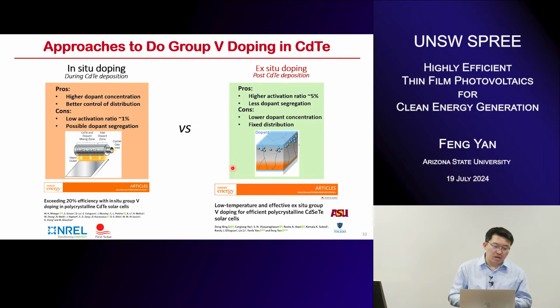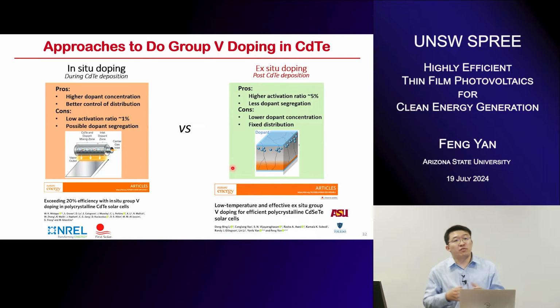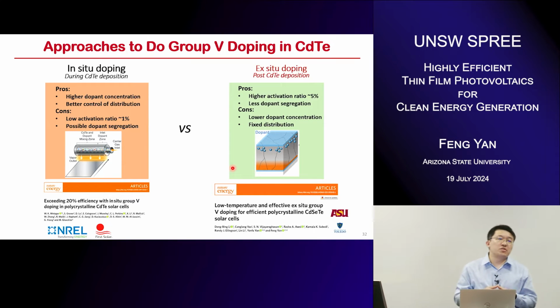The good thing is that the dopants are pretty uniform, with better control of the distribution, because it's uniform during the deposition. But they also have some challenges, for example, a relatively low activation ratio for these introduced dopants, and they also generate dopant segregation in the film.